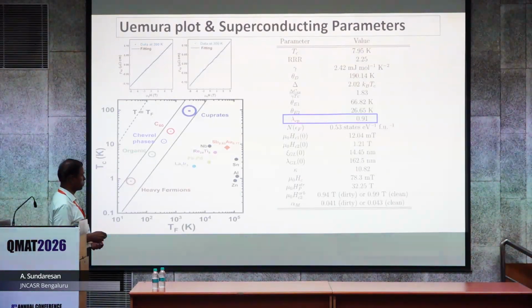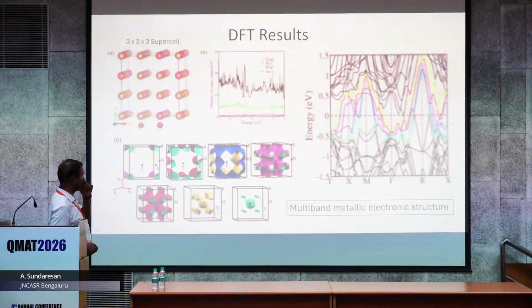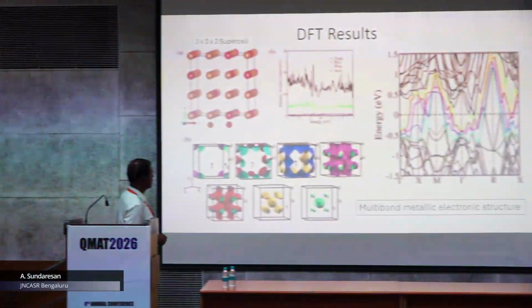The electron phonon coupling obtained is close to 0.9, and with the help of Professor Vaidiswaran we did DFT calculation. I'm sorry for this slide, I think it's too much stress - because of the disorder, he took a 3 by 3 supercell and obtained the electron density of states.